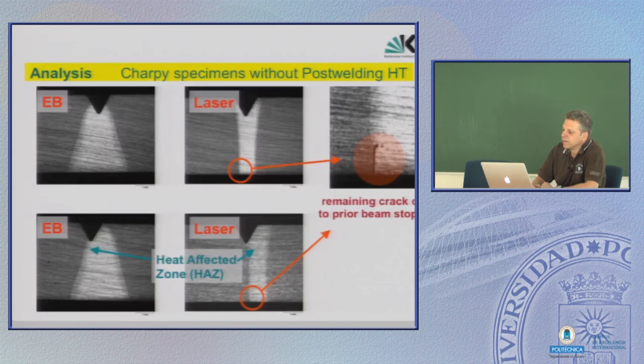Again, these are things you usually should avoid, these leftovers of the beam stoppers, and this is quite difficult to perform with laser, this kind of laser welding, because it produces a very narrow weld line. You always have to target perfectly on this weld line. But let's leave this beside.